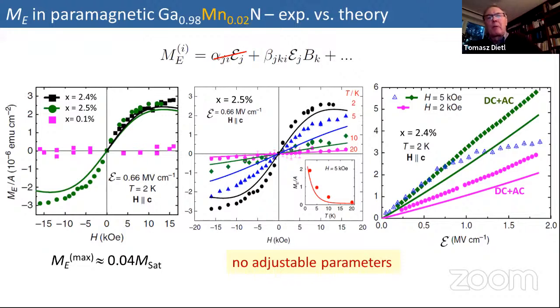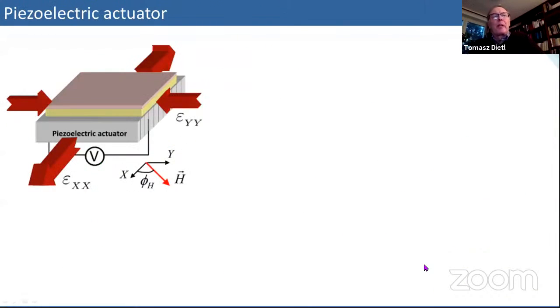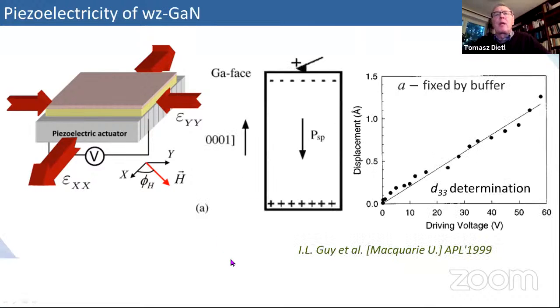But the solid lines are actually theoretical. I said that we know a lot about the system, so we can calculate what we expect theoretically with no adjustable parameter. And you can ask the question, what is the main mechanism for this magnetoelectric effect? Many of you, maybe in the audience, were using a piezoelectric actuator to deform a magnetic system to see how magnetization reacts, how magnetic properties change if you apply strain. So this actuator was used to strain our magnetic system. But what is nice about gallium nitride is that it's actually a piezoelectric material.